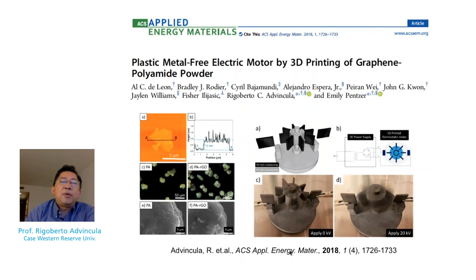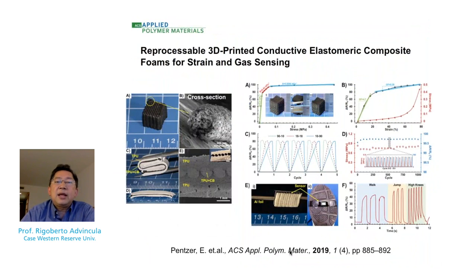So with these two last examples, we recently published a 3D printed electric motor. So this was done by using a nylon powder together with a graphene composition that we made together with the Pentzer group. So what happened is basically a plastic that behaved as a motor, a DC motor, an AC motor that we applied a high voltage though, but still is a moving motor where we incorporated the conductive material together with the plastic. And then finally, we recently published a conductive elastomeric foam for strain and gas sensing.